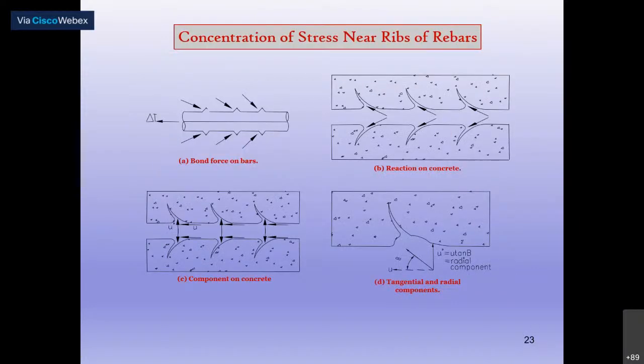So now that is one thing. The important thing here, when you relate this with cyclic loading. See, now this is your reinforcement bar embedded in concrete. It's fine for bond improvement. But actually, when you try to pull, what exactly is happening? This is the rib protrusion, the deformation. In front of this, the stress levels are so high. Suddenly the cross section is increased, and the stress flow changes. Due to that, in front of the rib, exactly the cracks will form.